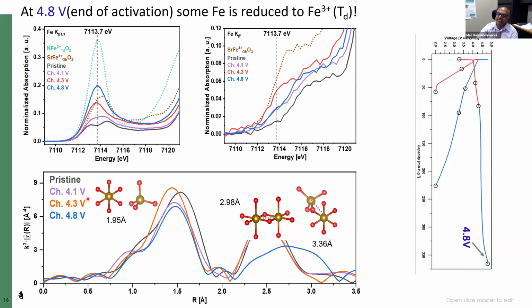Moreover, one can follow the distances that are there from the XAFS, and we believe that based on the measurements that we have done here using the K beta prime, the K beta 1,3, and the XAFS, that there is iron in the tetrahedral site. And more importantly, from the XAFS, when compared to the first 3 samples, the pristine, 4.1 and 4.3 volts, there is a significant intensity here, which can be clearly fit to an iron-metal distance corresponding to 3.36 angstroms. This distance is consistent with the migration of iron from an octahedral site to a tetrahedral site in this material.